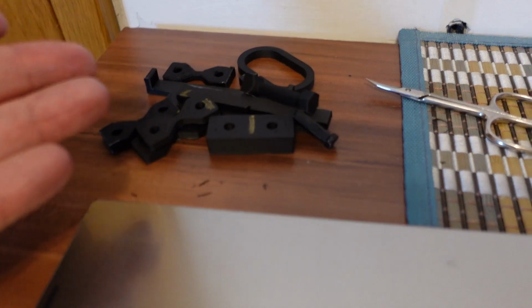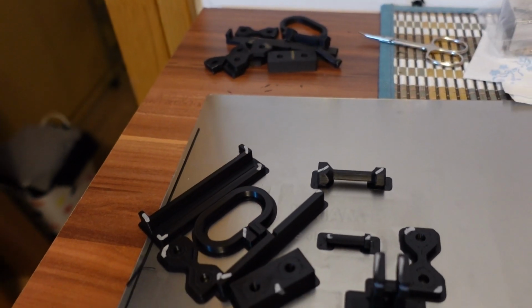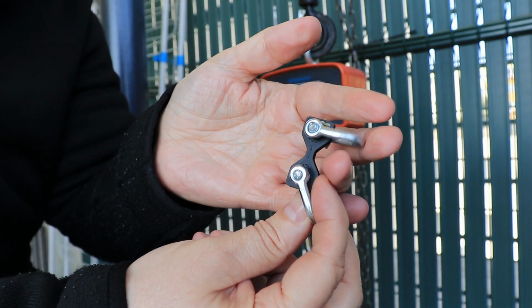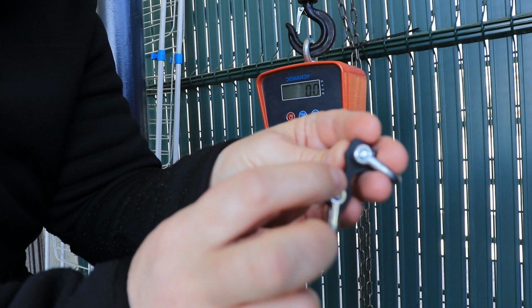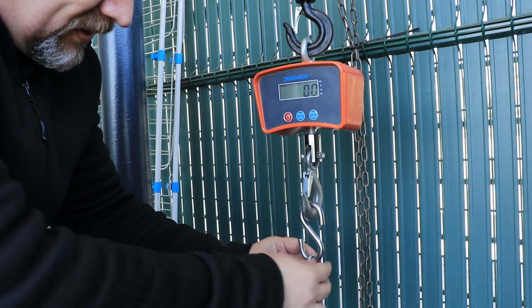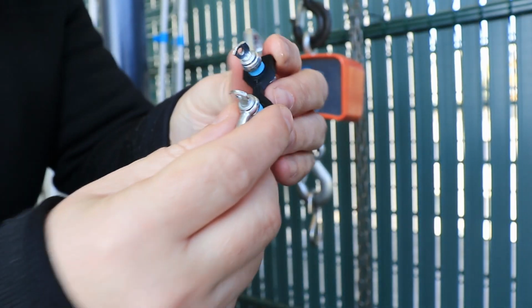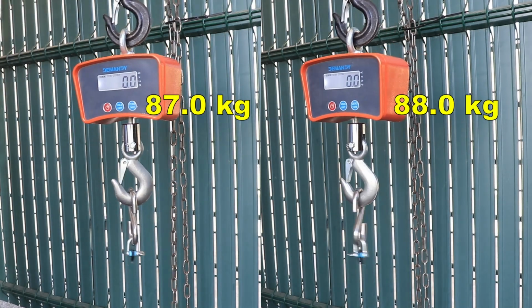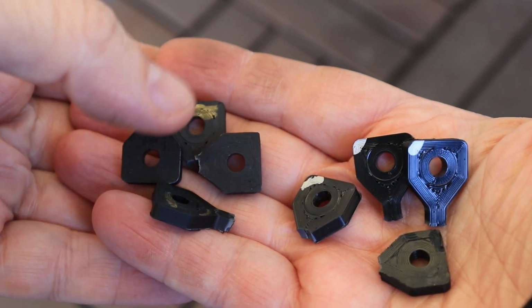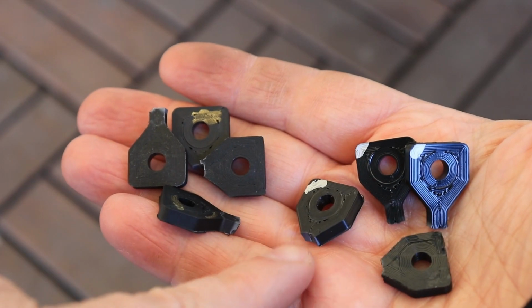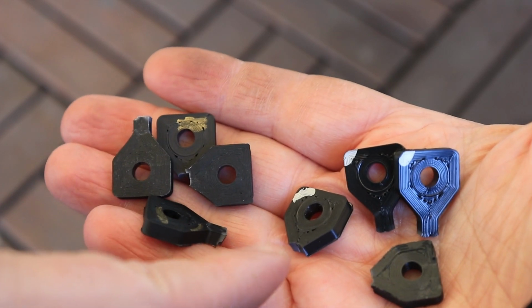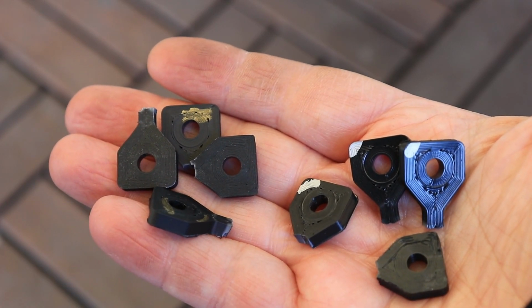And I have all test specimens printed, and now it's time for mechanical tests. Starting with tensile test, this is ABS Plus, 4x4 mm, the smallest cross-section area. And this is now ASA. And this is how they broke, all on the smallest cross-section area. This makes me think that the layer adhesion is okay, but we will find out in the next experiment.